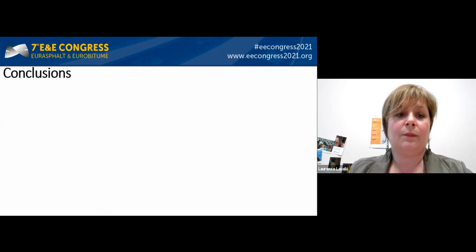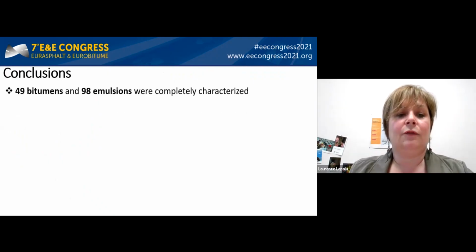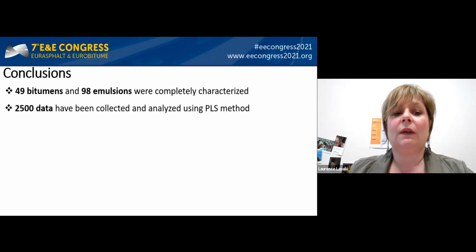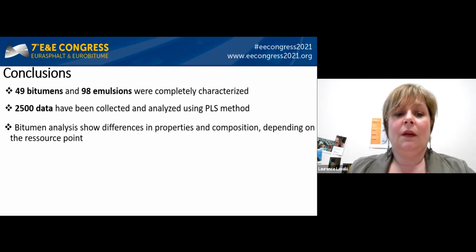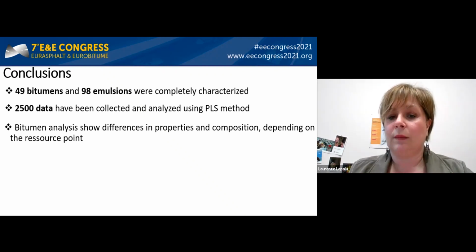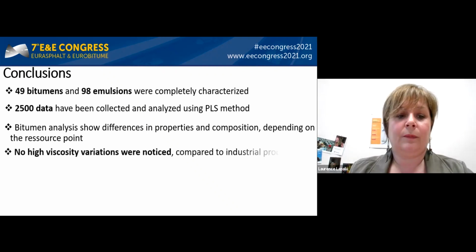properties of the emulsions. In conclusion, we have collected 49 bitumens for this study, and we have manufactured and completely characterized 98 emulsions. We have generated more than 2,500 data, and we have used a statistical analysis to analyze all this data. The bitumen analysis shows differences in properties and composition between the different bitumens, depending on their resource point. We didn't observe high viscosity variations for the emulsions that were produced at lab compared to the industrial production.